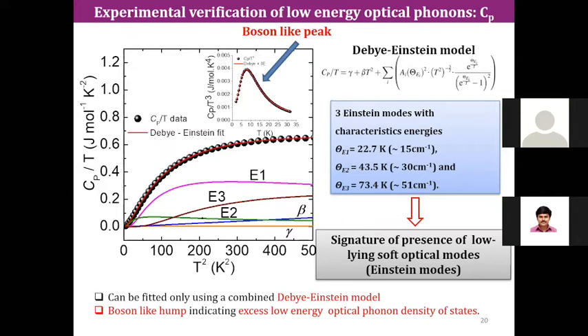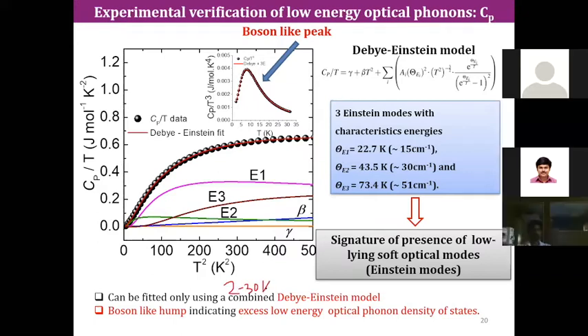This is the low temperature heat capacity data in the 2 to 30 Kelvin range, and this low temperature heat capacity data cannot be fitted by the Debye model alone. This is the Debye part, and this is the electronic part. So this Debye plus electronic part cannot fit this data. So we have to invoke the Einstein mode. This is the Einstein mode in this equation, and once we have the Einstein mode, this low temperature heat capacity data is fitted extremely well.